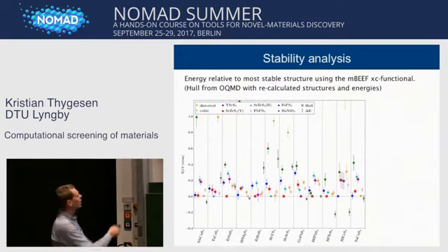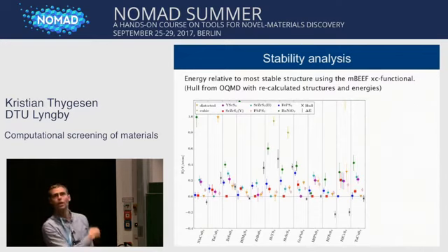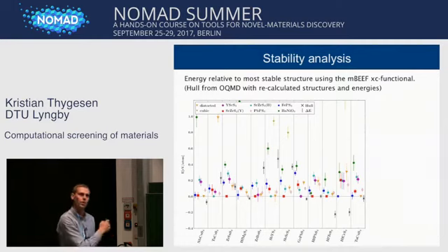So in this case, we will discard niobium copper sulfide, and not work anymore with that material because the convex hull is actually, or all the structures we are looking at are thermodynamically unstable. Okay? But if we look over here, you can see there is 1, 2, 3, 4, 5 of the structures we are looking at, and all of them are more stable than the convex hull.